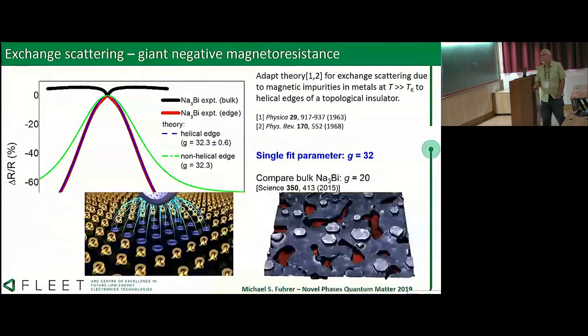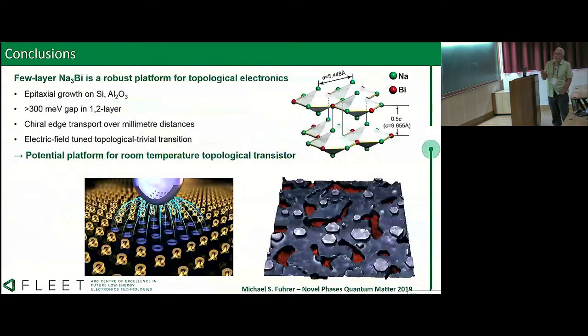Okay. All right, so that's all I wanted to say. I think this few layer sodium-3 bismuth is a nice platform for topological electronics. We can grow it on silicon and sapphire. It's got a huge gap, 300 milli-electron volts. It's much larger than room temperature. We see chiral edge transport over millimeter distances. And it has this nice electric field tuned topological to trivial transition, which we've already demonstrated. And so this is the kind of material that you could use for a room temperature topological transistor.